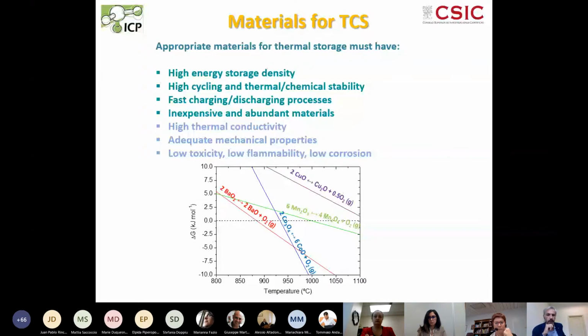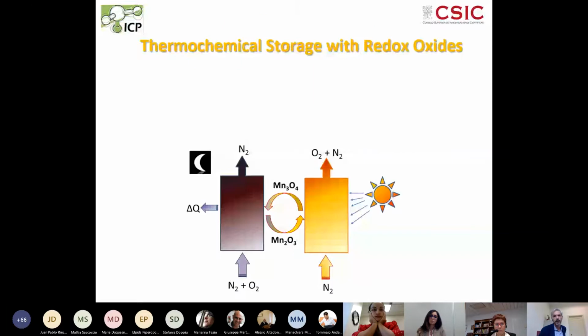So one important thing we need to see is the thermodynamic properties of these materials. Here we have several samples of several oxides that we can use for this application. As you can see, they have different temperatures for this reaction to proceed, and they also have a different slope in this plot of the free energy as a function of temperature. So in the case of the steeper slope, we are going to have a higher impulse, a higher driving force for performing these reactions. So thermodynamics is very important, as you will see in the next talks.